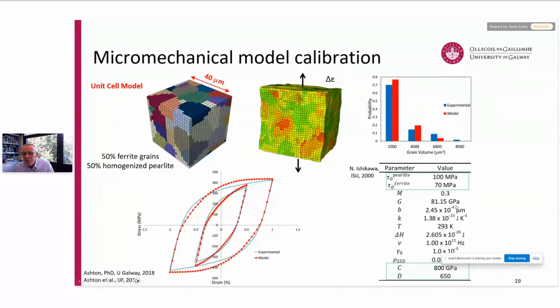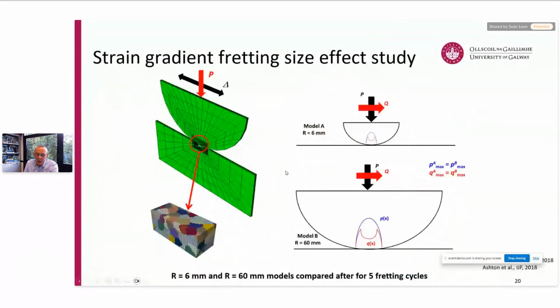We've calibrated those, and you can see in the bottom right that we essentially have 3 fitting parameters here. The critical resolved shear stress, or maybe 4, the critical resolved shear stress for the pearlite and ferrite, and then the C and the D, which are 2 parameters controlling the cyclic plasticity, basically. And all of the other parameters are physically based, essentially. And then you can see we're matching the microstructure if you look at the grain size distribution in the top right. And then we've looked at the so-called contact size effect for 2 different sizes of contacts, where the idea is the stress is kept the same. So the peak pressure and the peak shear are the same.